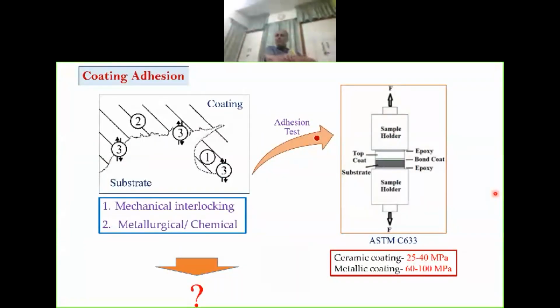Another perennial question. We have a coating and a substrate. The substrate doesn't melt, the coating melts. As long as it doesn't decompose, we can spray it. So anything on anything. We do not talk about metallurgical compatibility at all. So how do coatings adhere on the substrate? Can you measure it? Yes. How do you measure it? We take a substrate and coat, glue both ends with two anvils and pull them apart.